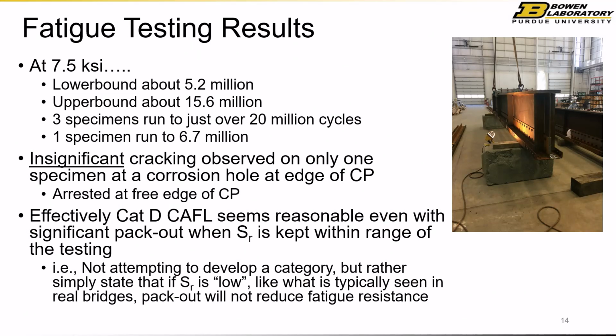Now, again, scatter and riveted members usually do better than D, but that's where the data fall out. So that means we have to run these specimens out up above 15 million cycles. We chose to run even higher, up to 20 million cycles. Now, remember, these already had 75 years of life on them in service. Now, what happened? Nothing. Right? There was no cracking that you could point at and say, yep, see, the pack out killed our fatigue resistance.